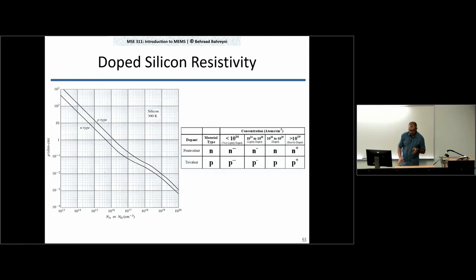Our typical doping levels are between 10 to the 16 to 10 to the 19. This is the sweet spot, about 10 to the 17 to 18. This is where we make most of our p-n junctions. If you want to get highly conductive regions, you dope them to 10 to the 19 or higher. And if you want areas that are almost insulating, you make sure that the doping level in those areas is below 10 to the 15 or 16 if you can manage it.